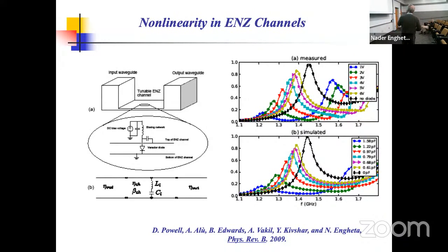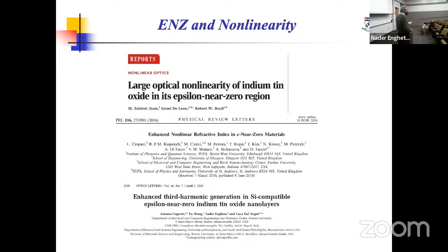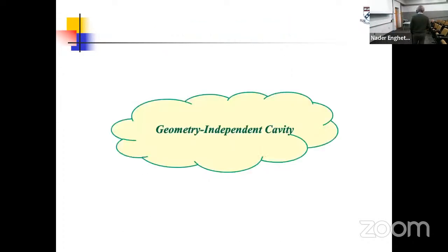But just recently, several groups started actually looking at this nonlinearity, particularly in the near IR. And so my friend Bob Boyd showed the large optical nonlinearity in ITO, indium tin oxide. And Vlad Shalaev, Alexandra Boltasseva, and Daniele Faccio also showed that there is an interesting, highly enhanced nonlinearity in AZO. And my group, together with Luca Dal Negro from Boston University, also showed the enhanced third harmonic generation that can happen in ITO.